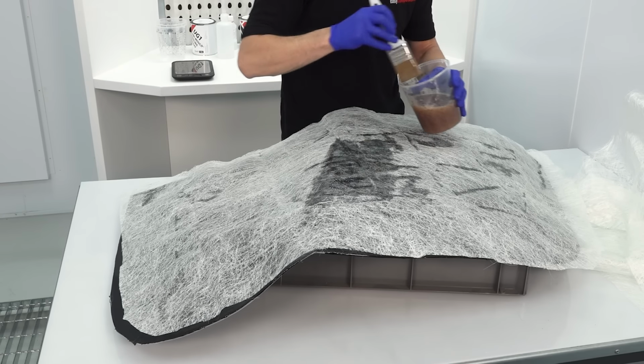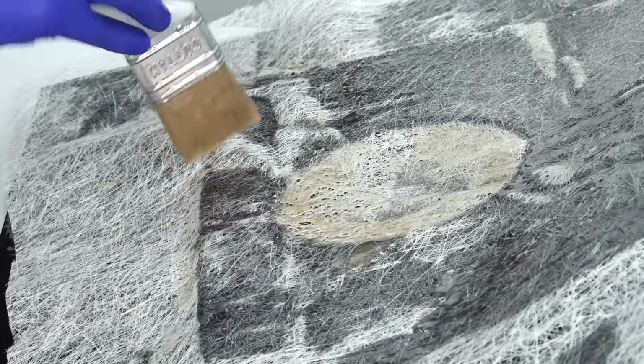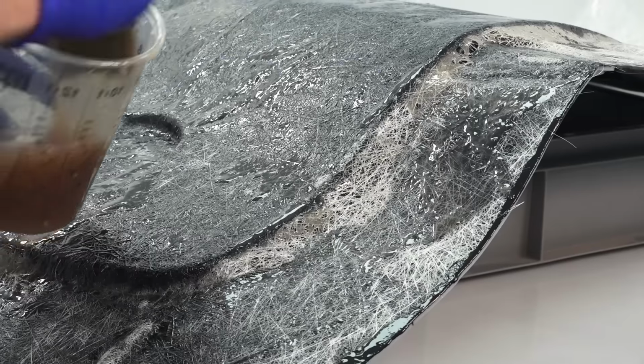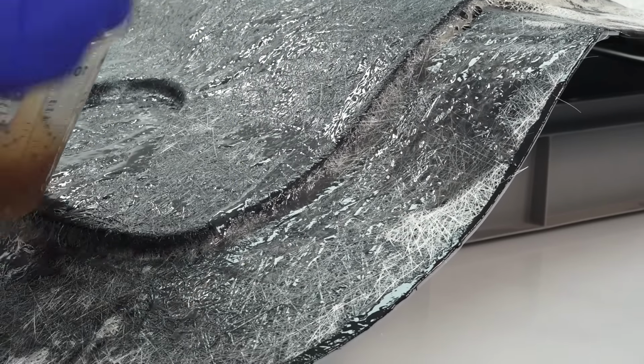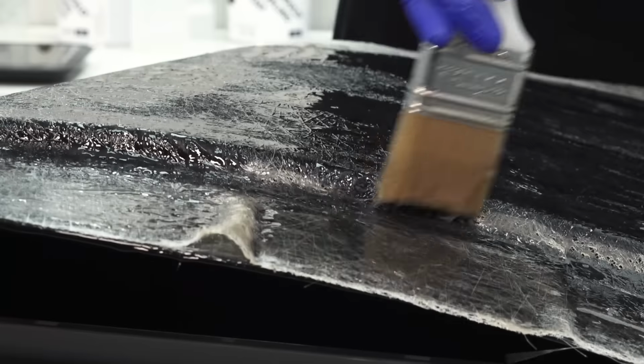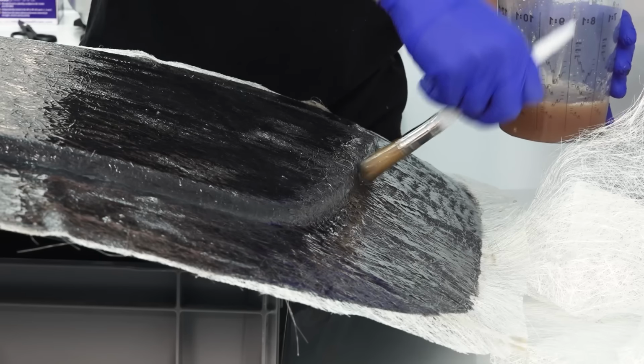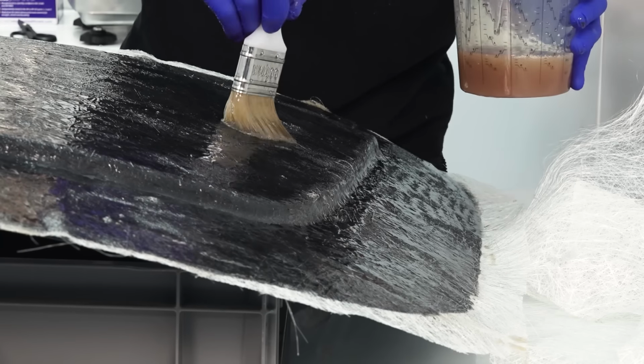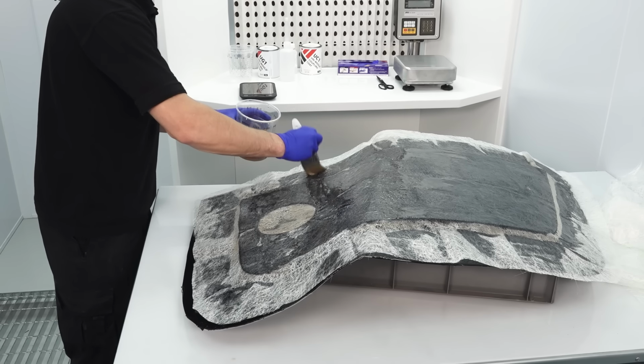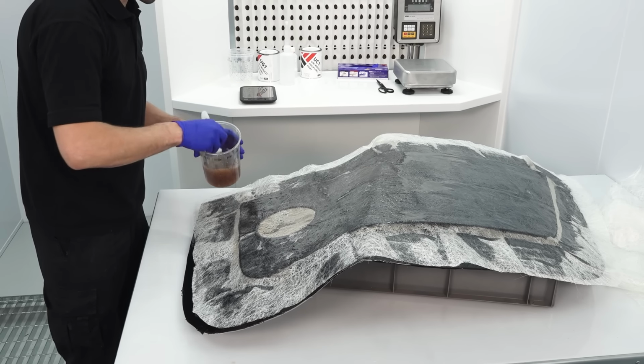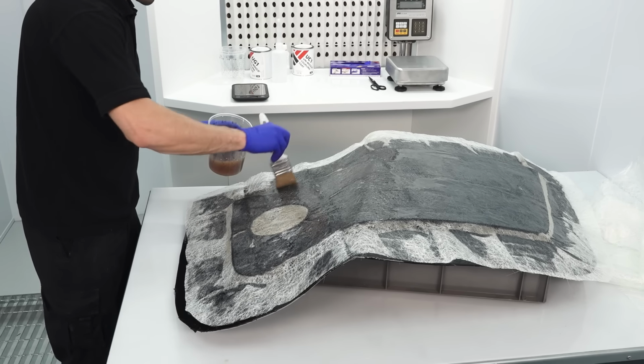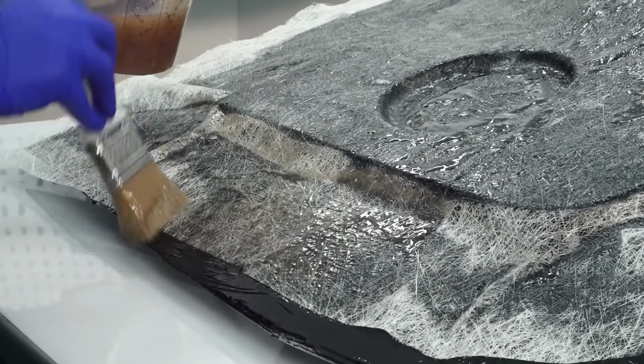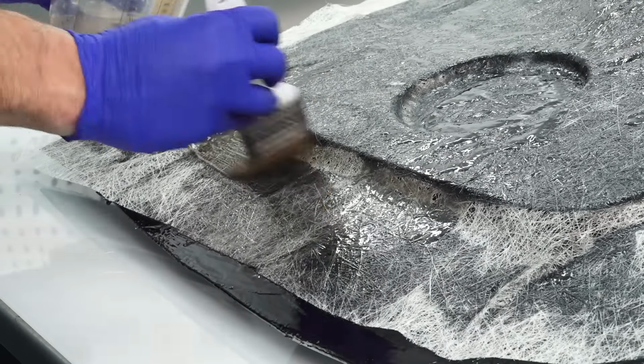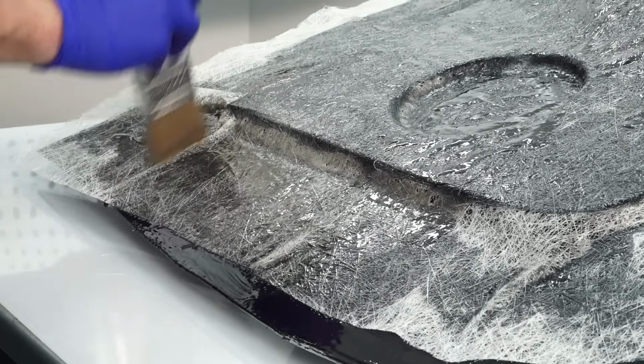This matting has a binder that holds the fibres together, and this binder then dissolves with the resin, meaning that you can first apply the resin with brush strokes, but once it's wetted out and saturated, you should use a stippling action to avoid moving the fibres around too much. When properly saturated with resin, the matting will be almost completely transparent. For these first 100 gram plies, generally only a brush is needed as they are a bit too thin for a roller to work effectively.